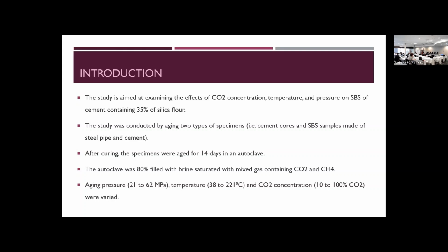On these samples, we've done bonding tests. We've done some other tests that I will present, which were used more or less as a reference correlation for our shear bonding. What you're going to see here will be samples which have been aged for 14 days in an autoclave, and they were tested after being extracted from the autoclave.